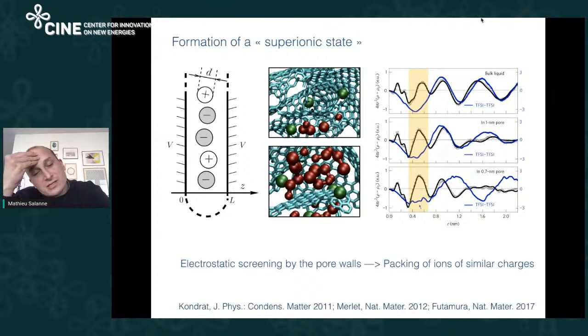So in fact, I think this is a very interesting example where we had some experimental studies in 2006, electrochemistry that was showing large capacitance. It was explained by theory 5 years later at that microscopic scale, confirmed by simulation 1 year later again, and it's only 4 years ago that we had an experiment that could really confirm this picture, that we were on the good interpretation of the results.